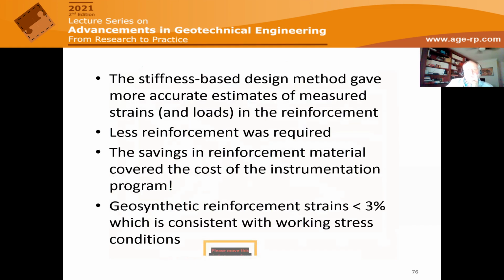So this, in addition to this design method, which gave us more accurate estimates of the measured strains and loads in the reinforcement, less reinforcement was required. And in fact, the savings in reinforcement material for these two walls covered the cost of the instrumentation. And the other thing that was shown in this structure was that the reinforcement strains were all less than 3%. The highest were about 2%. And this is consistent with the notion of working stress conditions that I mentioned earlier are a prerequisite to keep these structures under operational conditions.